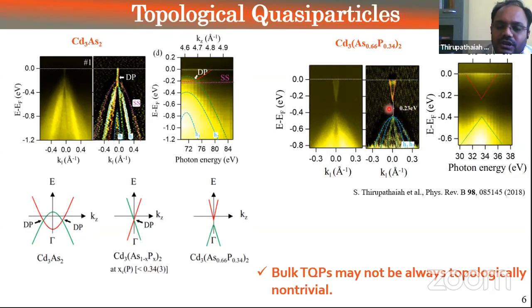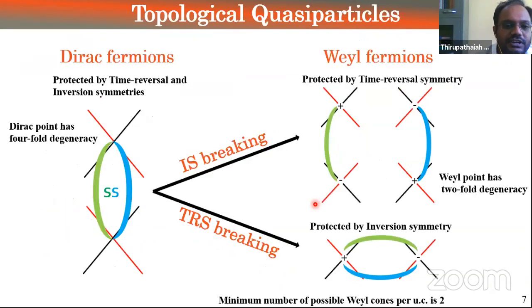So usually when we call something topological, if the Dirac point is not disturbed, then we call it topologically protected. But just by disorder, it's being disturbed. So I think these 3D Dirac points are not always topologically non-trivial. This is one of those examples which we studied earlier.